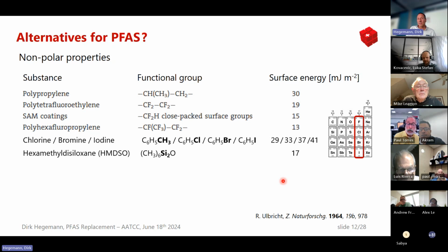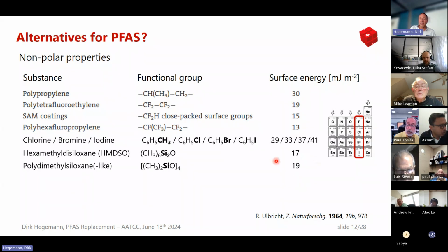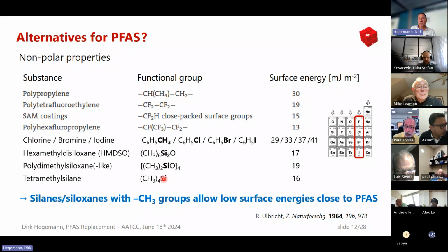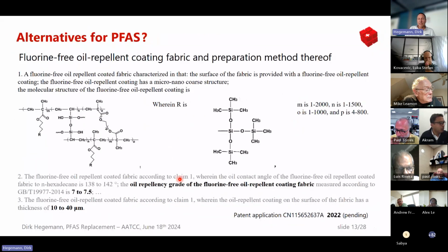What looks more promising is when methyl groups are bonded to silicon or silicon oxides or siloxanes. There you also have low surface energies, and the lowest when you have a high number of methyl groups bonded to silicon. So these silanes and siloxanes might indeed be the best selection to check their potential to replace PFAS. And when you look at the patent literature, indeed, meanwhile you find plenty of activities, and some also claim very good oil repellency, using a kind of hierarchical structure. Many of these SiCH3 groups decorate bonds to siloxane, and this is the R group here that is fixed to this hierarchical structure of, let's say, a siloxane chemistry. That is a viable approach.